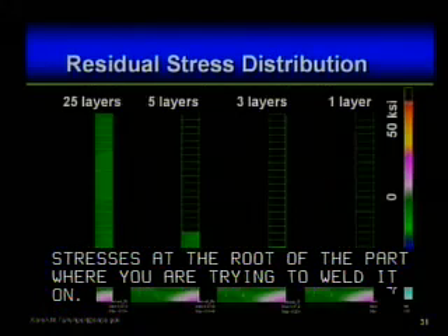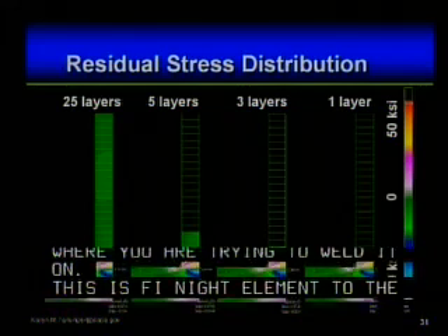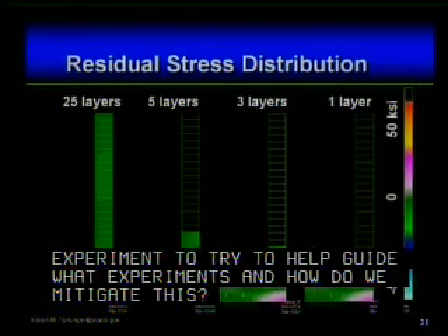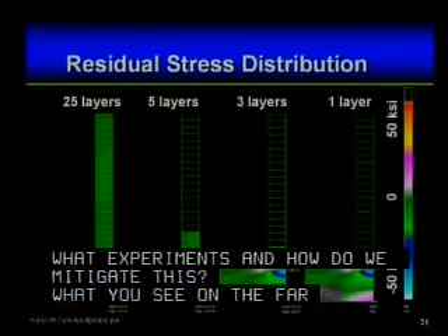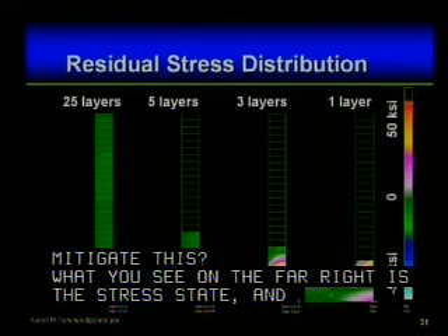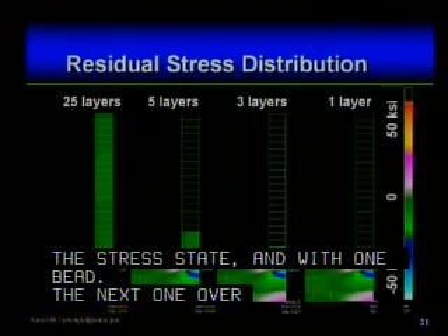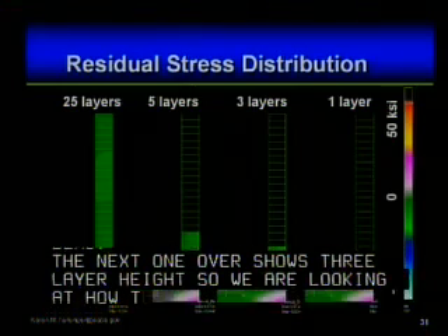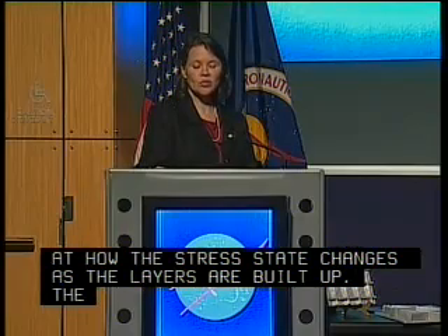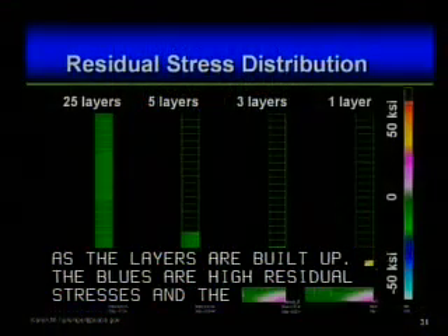Next slide. So this is a series of finite element modeling experiments that we've run, and we've been comparing finite element to the experiment to try to help guide what experiments to run and how we mitigate the residual stresses and the distortion that's developing in the material. Across the bottom you see the base plate, and what you see on the far right is the stress state with one bead. The next one over shows 3-layer height. So we're looking at how the stress state changes as the layers are built up. The blues are high compressive residual stresses, and then the pinks are the tensile residual stresses, counterbalancing that.